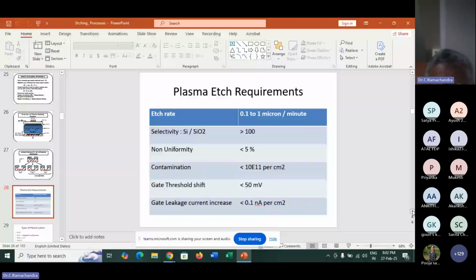So what are the typical plasma etch requirements? Selectivity. Suppose I want to etch silicon but not silicon dioxide, or I want to etch silicon but not aluminum, any adjacent material. Typically the selectivity is more than 100 in industry. Etch rate: typically 0.1 to 1 micron per minute, because most of the time our etch thickness will be less than 5 micron. Even at 0.1 micron per minute, it will take 50 minutes. That is not affordable; industry production will be affected if it takes a very long time. Then non-uniformity: throughout the wafer, you should etch uniformly. The non-uniformity acceptable in industry is typically 5%.